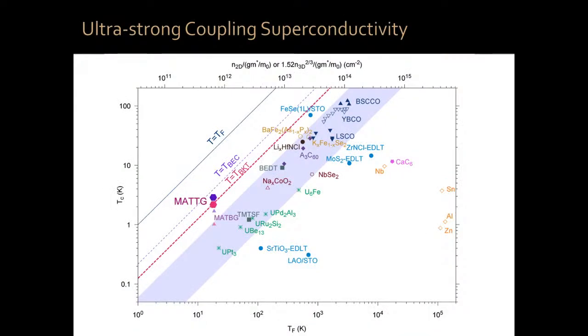the superconductors which are strongest, in some theories, the reason why there are these dashed lines is because in some models, this is a limiting factor for how strong it can be. It turns out to be not a strict limitation, and it depends on the type of system that you have, but it serves as a guide. As you can see, the vast majority of superconductors are below that line, okay?